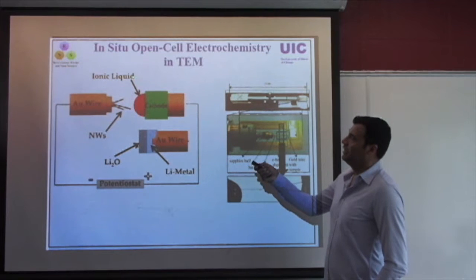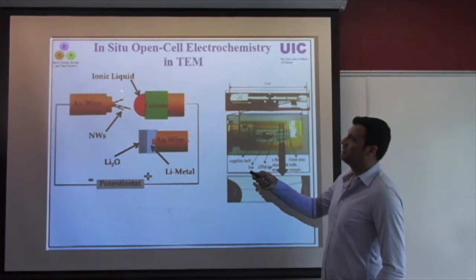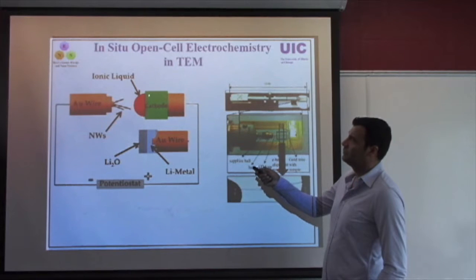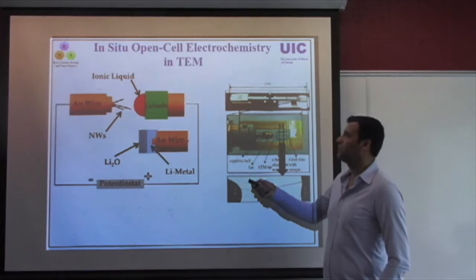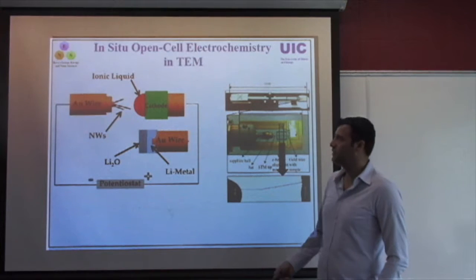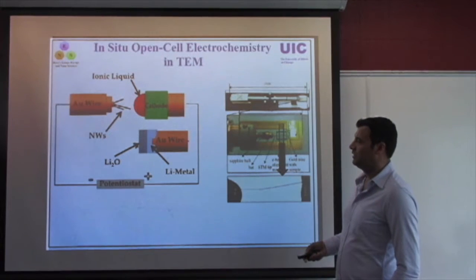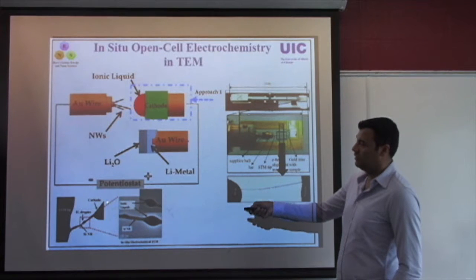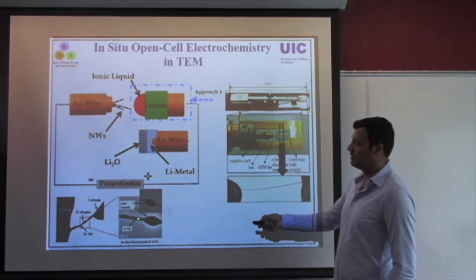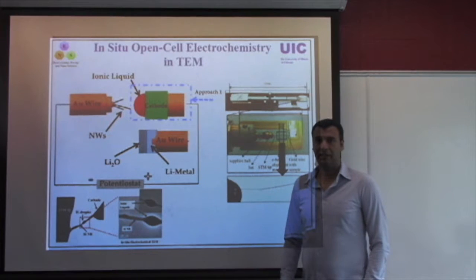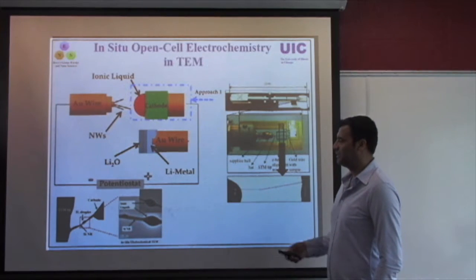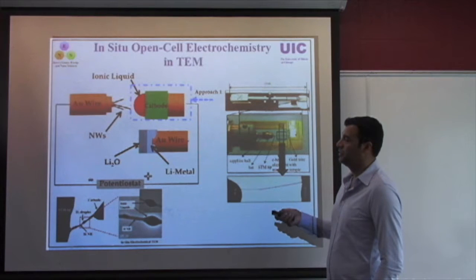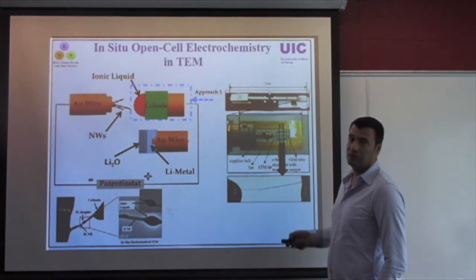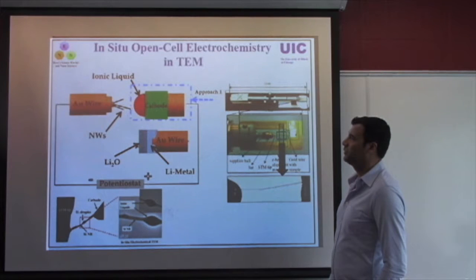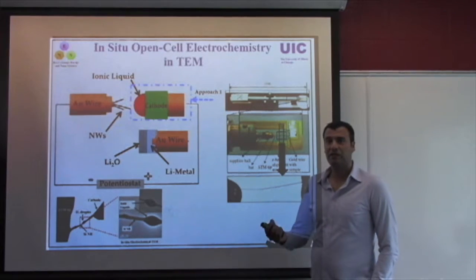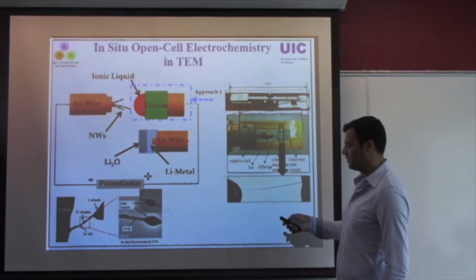A kind of electrolyte family that is very compatible with the vacuum condition of the electron microscopy is based on ionic liquids. We have tested this system before, and this is an example of materials we tested with ionic liquids. They can stay intact for several hours while you do electrochemical research. So that's something we recommend if you want to look into electrolyte and if you care about flooded geometry during the electrochemical reaction.